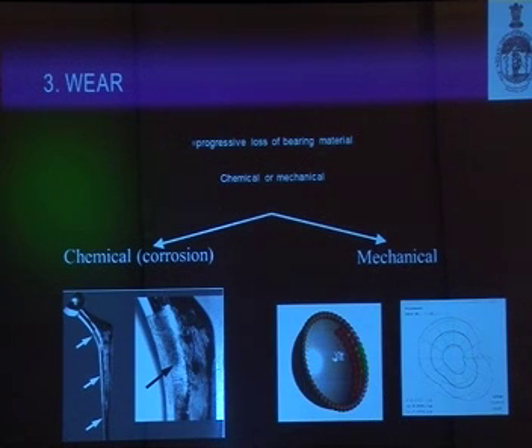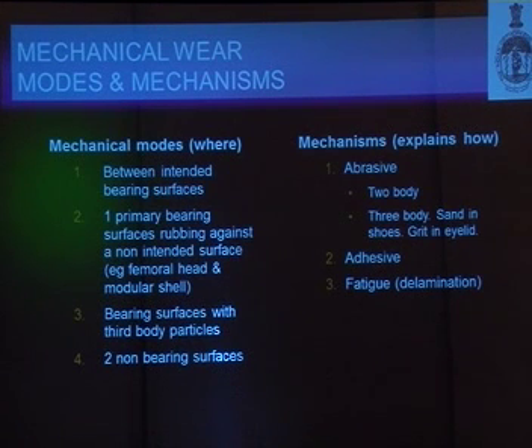But that brings us to wear, which is a progressive loss of bearing material, quite similar to the radiographs we saw initially. Could be chemical, which is corrosion, or could be mechanical. The mechanical wear is between intended bearing surfaces, like a femoral head and a modular shell rubbing against each other, or bearing surfaces with third body particles, which are the wear particles, or between two non-bearing surfaces. It could be either abrasive, which is a two body wear, or three body, which is like the sand in a shoe, which is the extra asperities, or adhesive or fatigue, which is the result of delamination, more in total knee arthroplasty.